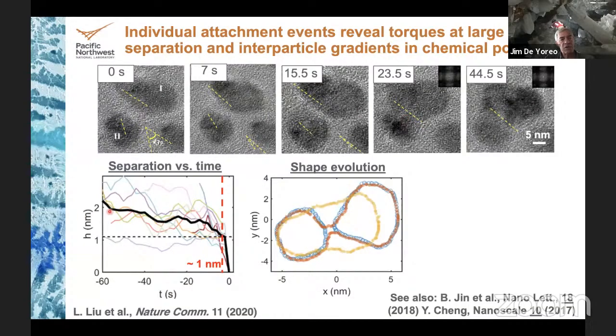We can look at the separation versus time, and I'm sorry, I did this in time, and in many ways it would be better if I did it in distance. But you can see the continuous attractive interaction until they get to within about a nanometer when they jump to contact. The other point I want to make is if you look at the shape evolution, the blue outline is particles before they touch. Now if you look at the red curve, instead of touching, these two particles have grown a neck.